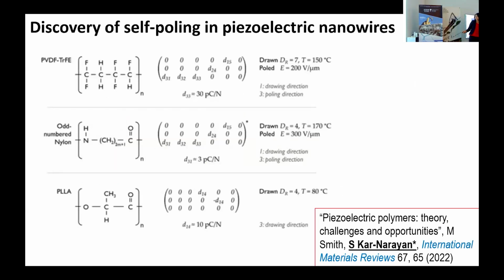So this is this nice review paper that we published a couple of years ago, where we show how the polarization is induced, usually either by drawing or by poling. You can see large electric fields are required. This is the case for PVDF, nylons, polylactic acid. This particular material is not ferroelectric, so you cannot actually pole it. So the only way to actually get inducement is by drawing.